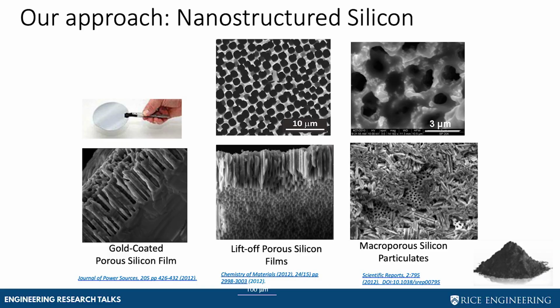We borrowed a process from the semiconductor industry where you can have large quantities of silicon wafers that you can electrochemically etch to create porous silicon. What's nice about our material, we actually went through many generations of this. What's nice about it is it has a very high surface area, on the order of about 300 to 400 meters squared per gram. So very high surface area material.